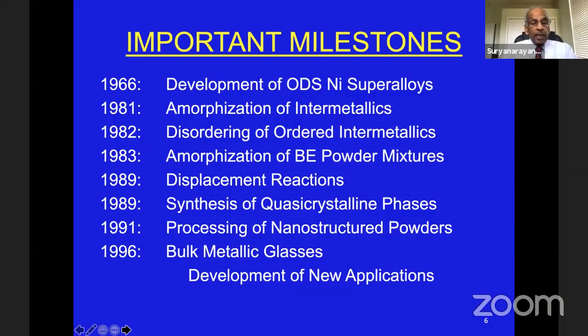There are many developments, but the most important developments that took place in the area of mechanical alloying are these. The technique started in 1966. That means a little less than 60 years ago. And this was used mostly to produce oxide dispersion strengthened nickel-based superalloys. Then it was extended to iron-based superalloys and then aluminum alloys. Like that, it slowly diversified to different areas. But originally, this was developed in 1966 for ODS superalloys, especially for high temperature aerospace applications.